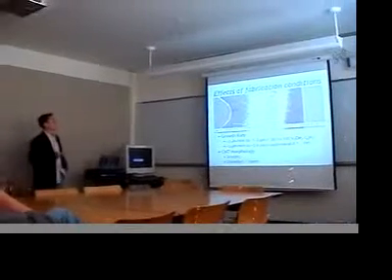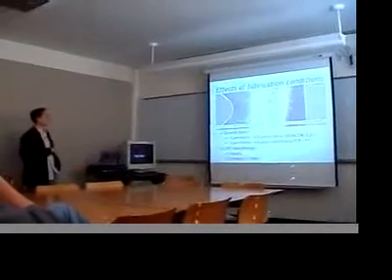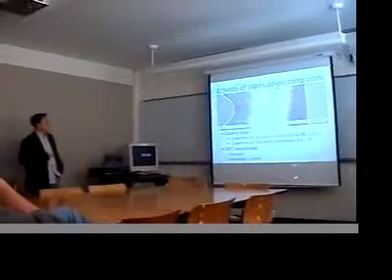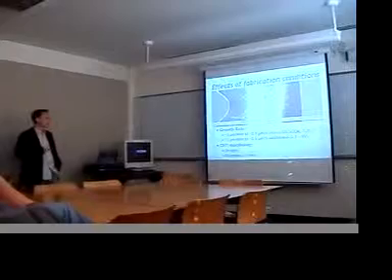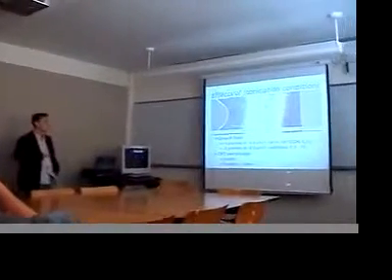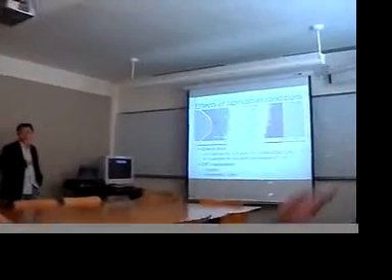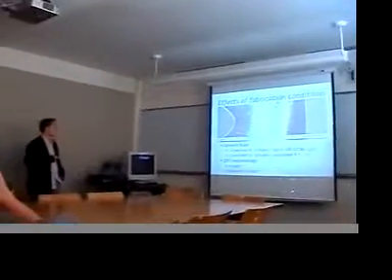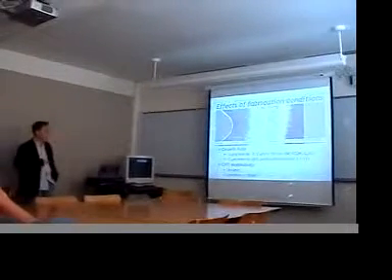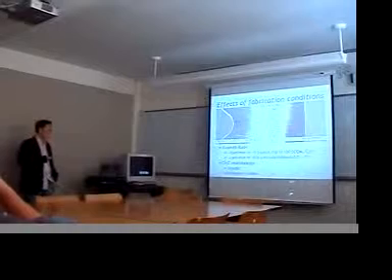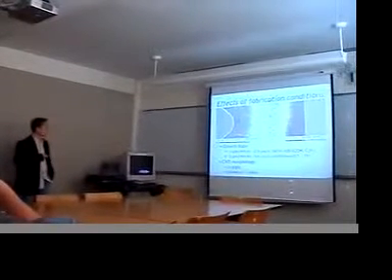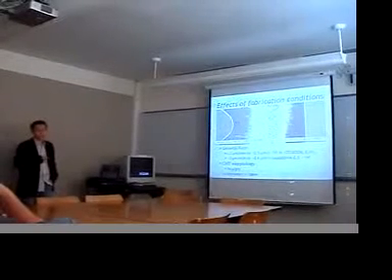We also play around with the fabrication condition. When we increase the gas flow and the temperature, once again, I don't have a very good idea of how high exactly it is, but typically we raise around 0.5 to 1 volt more than the initial growth condition. You can see that the CNT growth rate actually increased by quite a lot, more than 10 times. Typically, this CNT connection is made in less than 10 seconds.